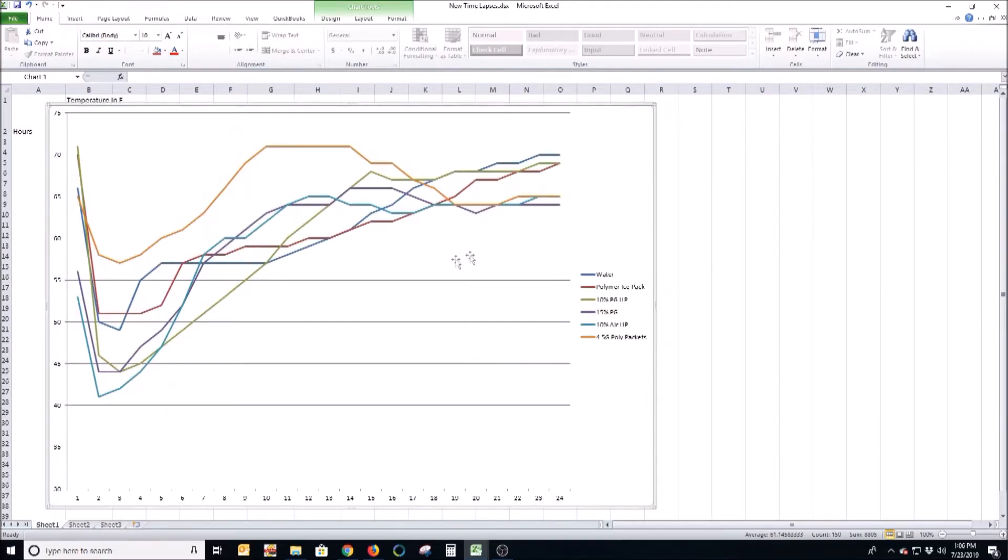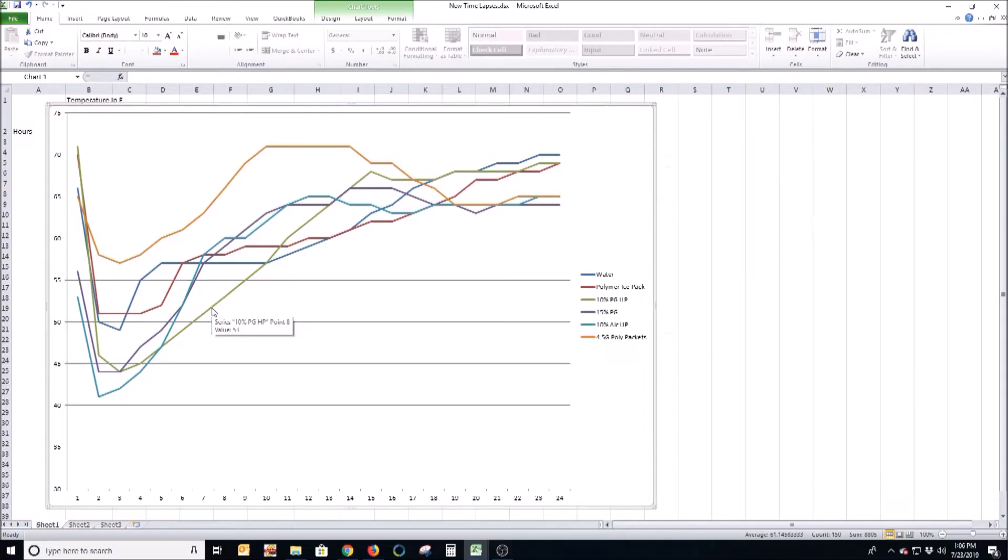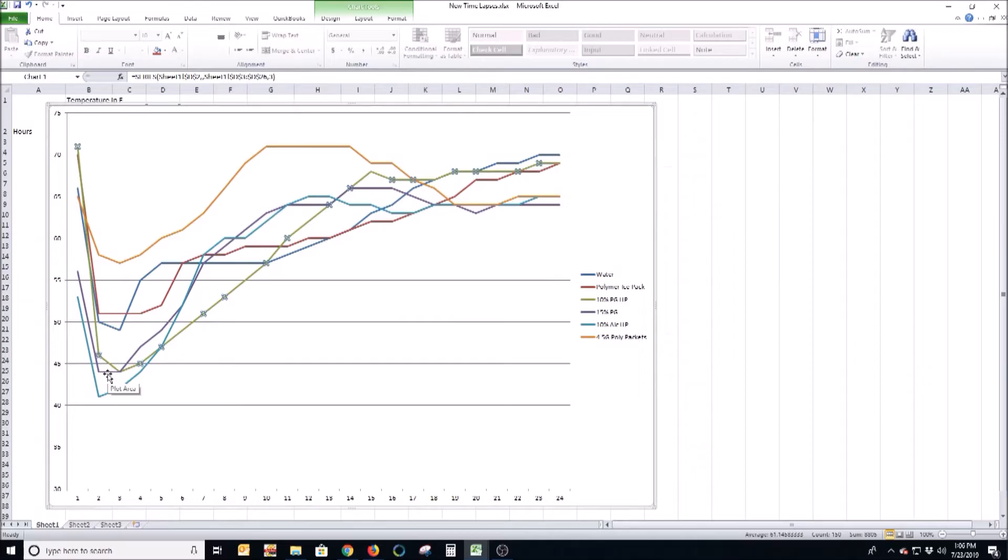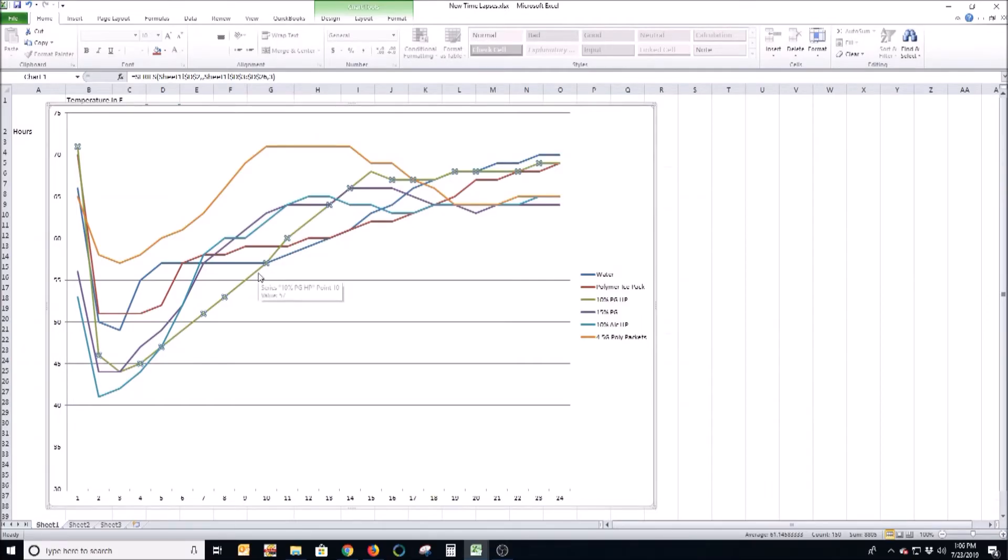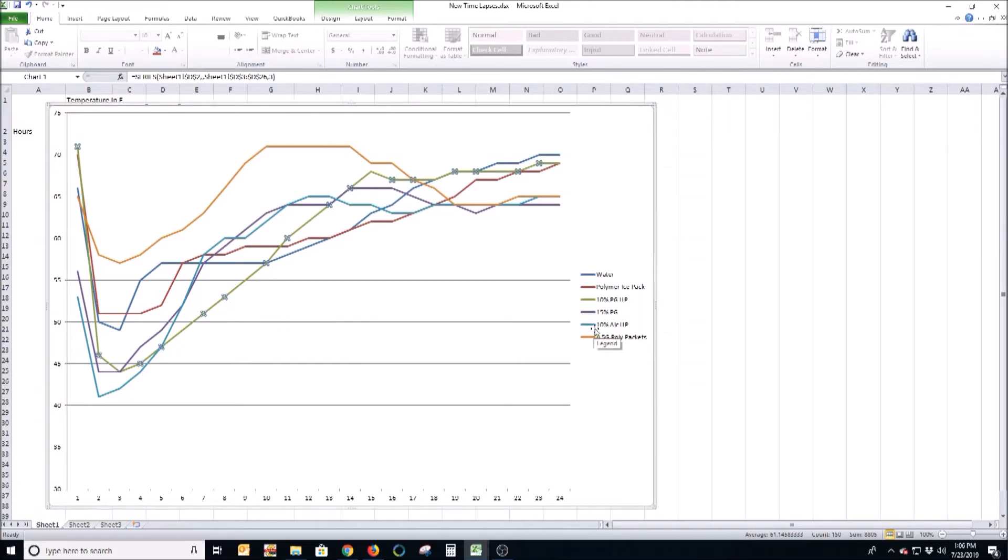And what we got was pretty interesting because what it shows was that the 10% alcohol got colder, but the one that lasted the longer was really the 10% PG. If you see this line right here, it didn't get quite as cold as the other ones but it did last longer and kept the cooler longer. This test I ran a little differently - what I did for this test was take the ice pack that I created with these mixtures and put it on one side of the cooler and put the thermostat on the other side of the cooler. And the intent was to see how long, or how cold and how long it would keep the cooler itself.